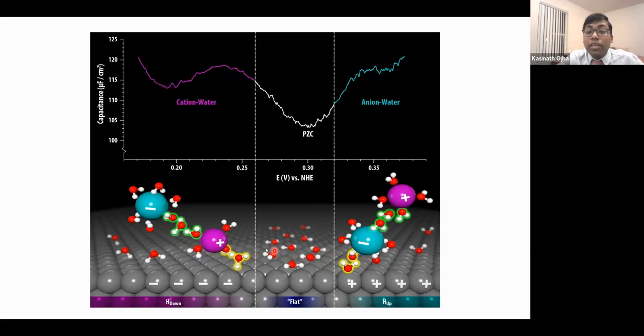And in between, you have a zero charge condition where your surface doesn't have a charge. That's exactly the potential of zero charge condition. And at that time, water remains flat. And once it is flat, it doesn't really interact with the ions so strongly. And at that time you see a minimum in the capacitance curve.